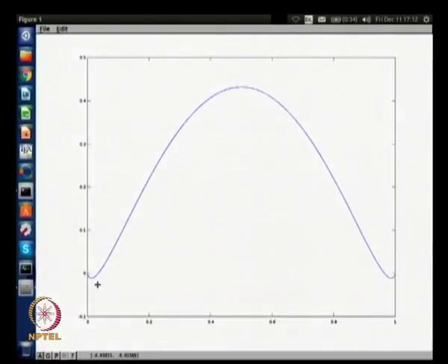So, the end points will always be like this, but otherwise you will see the free energy coming like this. So, the free energy curve, it actually joins the y axis parallel to y axis. Okay. So, if you try to take the slope at these two extreme points, that is like infinity, and that is why we skip them while plotting, because that will give you not a number. So, that is going to join like with infinite slope. Okay. So, this is with respect to different alpha values, how the regular solution free energy of mixing looks like.